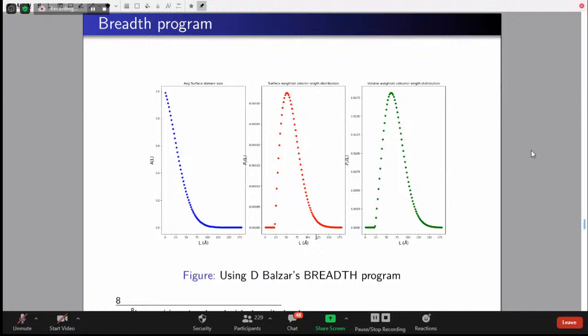But this distinction only the experimentalist knows, who knows the history of the sample. If I have a sample with a larger number of dislocations, I should attribute this effect to the dislocations. But if it is more of faults, then I will attribute it to the faults. So there is no straightforward definition for what is contributing to what. But this can be done with the Warren-Averbach method, where you are able to see the surface domain size,